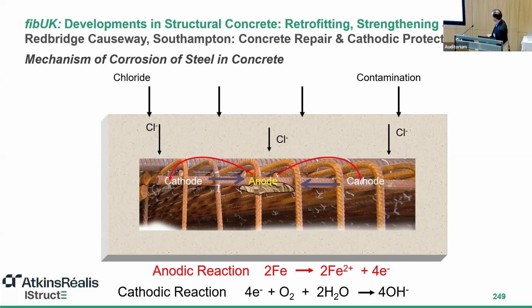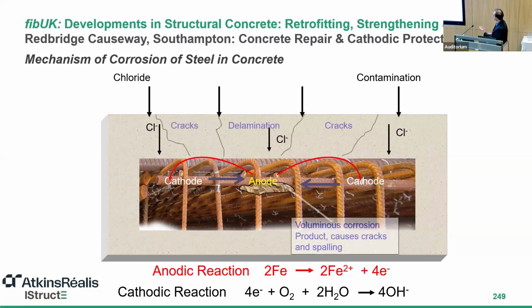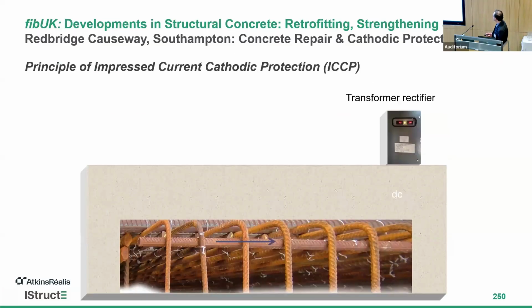And as a result, the iron gets dissolved and oxidized to different forms of oxidation, and that's where we get the expansive corrosion products, and that's the main cause for cracks, delamination, and spalls in concrete. So cathodic protection is an electrochemical technique proven over the years, recognized by BS EN 12696 and also National Highways standards, effectively by applying a DC current within the concrete and around the reinforcement. We're trying to reverse those reactions, the anodic and cathodic reactions.